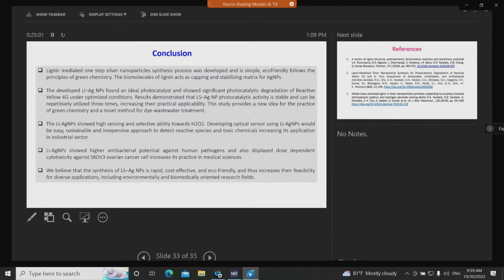Finally, based on these different applications of lignin-mediated silver nanoparticles in the area of photocatalytic degradation, the sensing of metals or hydrogen peroxide, and for anti-cancer activity and antibacterial activity, I would like to conclude that the lignin-mediated one-step silver nanoparticle synthesis process that was developed is simple, eco-friendly, and follows the principles of green chemistry. And the biomolecules of lignin, like hydroxyl, carboxyl, and phenolic groups, act as a capping and stabilizing matrix for AgNPs.